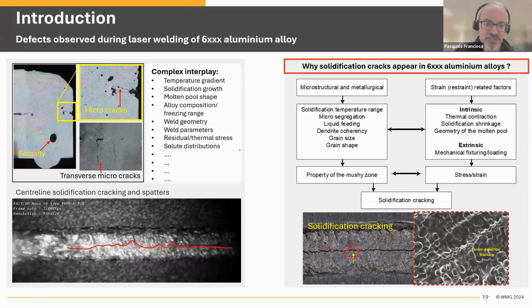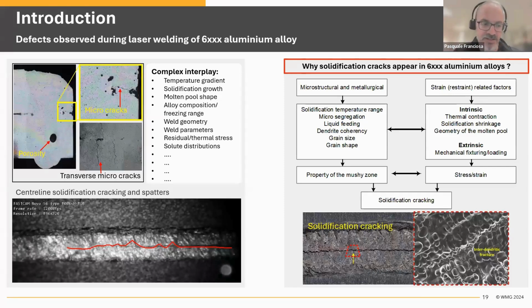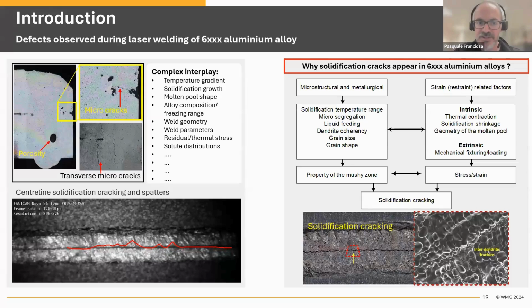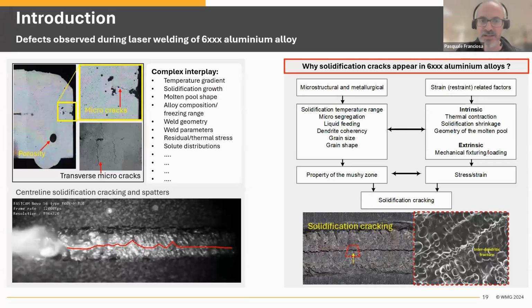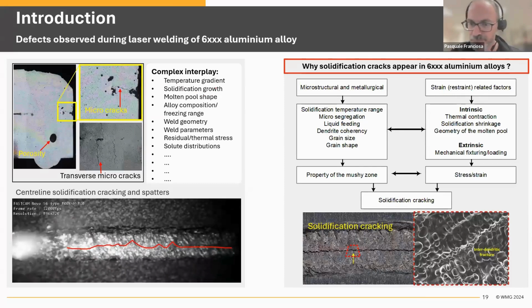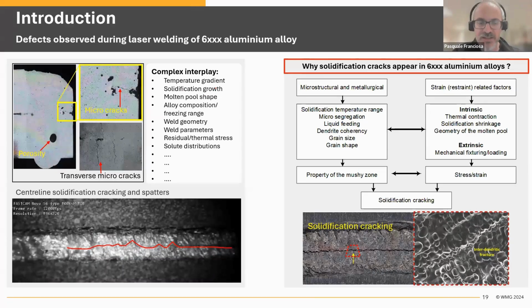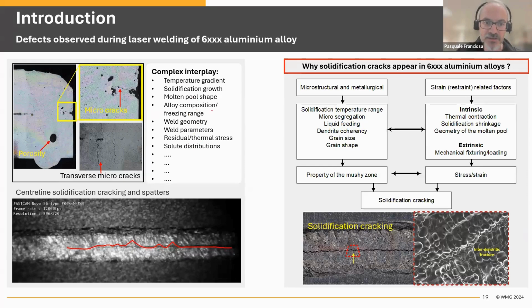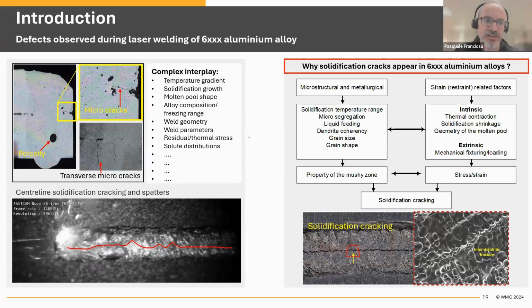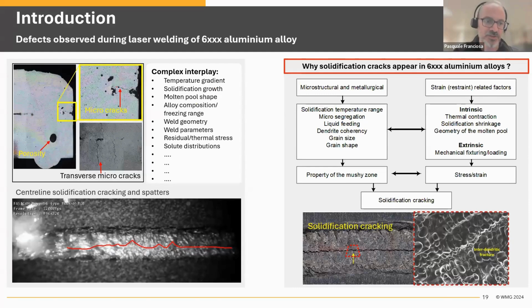There are some theories saying that the crack is happening because of the shape of the molten pool. If the molten pool is very stretched and elongated, there is more crack sensitivity. If there is a chance of reducing the extent of especially the mushy zone, there is a chance of reducing the crack sensitivity. Other theories talk about the combination of thermal gradient and solidification growth, so the cooling rate. Other research says the cracking is happening because there is not enough feeding of liquid between the dendrites, and that is causing micro pores. Those micro pores nucleate and grow, and then in the end you get micro cracks within the weld.